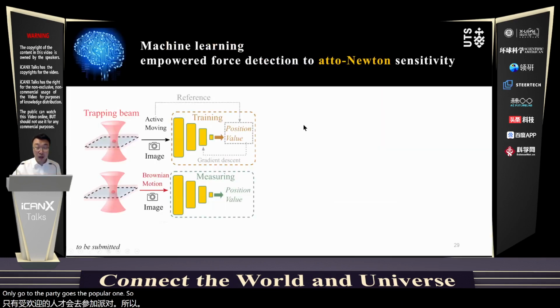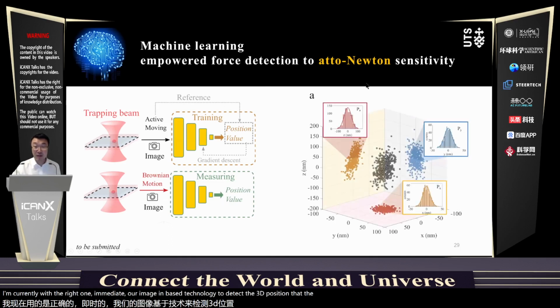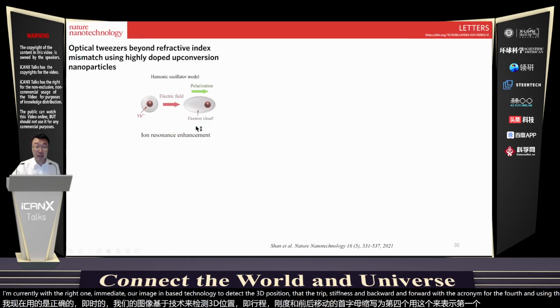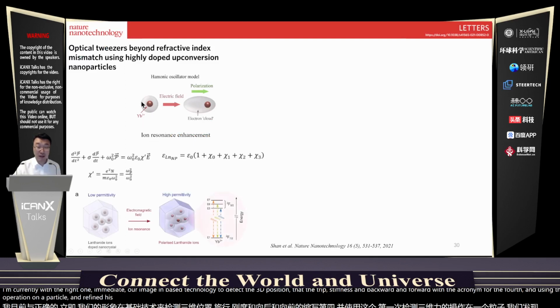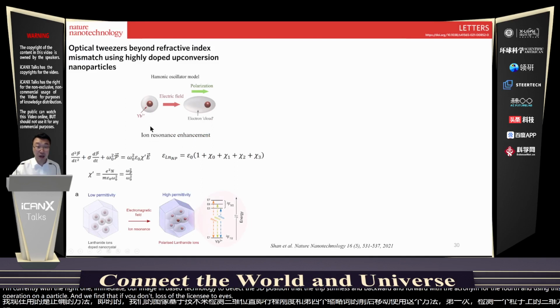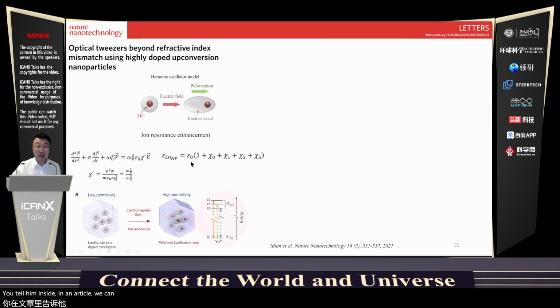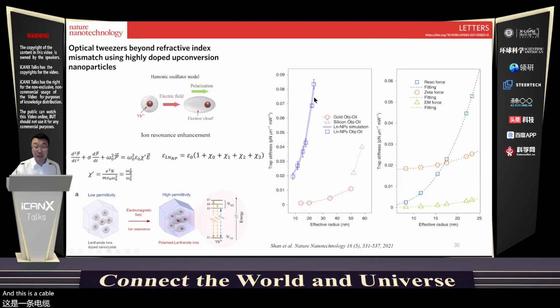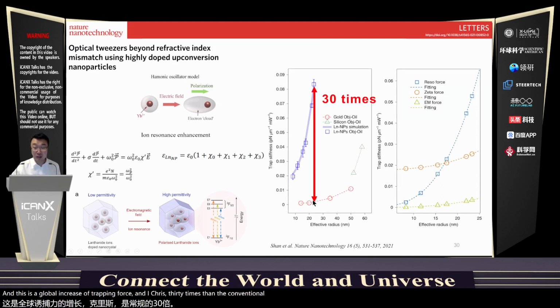So we developed an imaging-based technology to detect the 3D position and get the trap stiffness, and we can even go to the femtonewton force. Using this, for the first time, we detected the three-dimensional force for upconversion nanoparticles. We found that if we dope lots of lanthanide ions, ytterbium, inside the nanoparticle, we can increase the susceptibility and the permittivity. This gave an increased trapping force, actually 30 times that of the current gold nanoparticle. So it's a huge improvement.